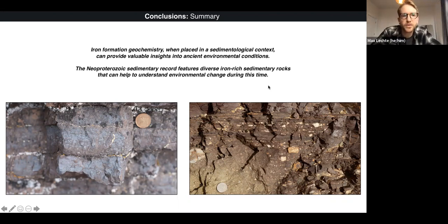Yeah, that's a good question, and it's definitely something that I've looked at. It's interesting, you don't see a lot of manganese in this, and that's the same for both the ironstones and the Neoproterozoic, the Cryogenian glacially associated iron formation. I showed, I think, one plot with the trends in manganese to iron ratios, but even then, it's really small. So potentially for these more suboxic to low oxygen conditions, that's suggesting that these are still below the oxygen levels required to preserve manganese in the sedimentary pile, and you're burying your iron oxides, but you're reductively dissolving the manganese.